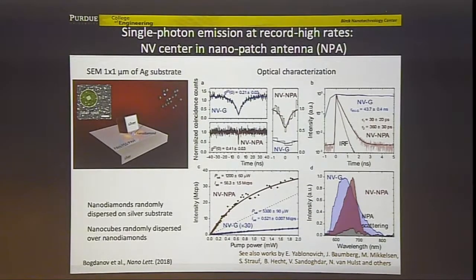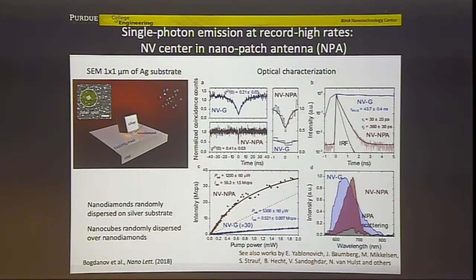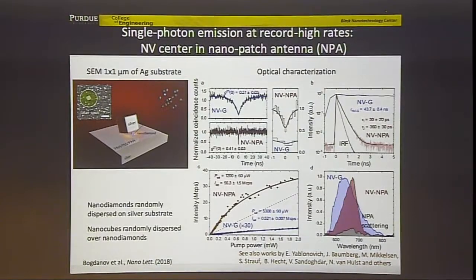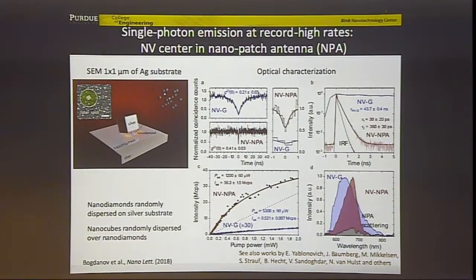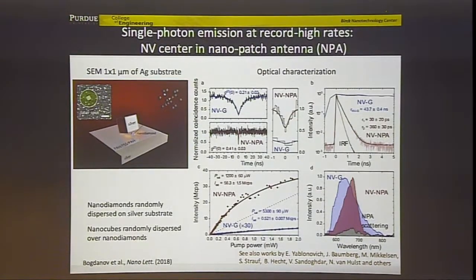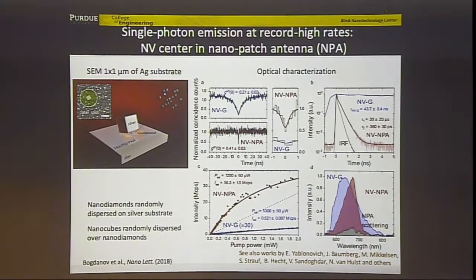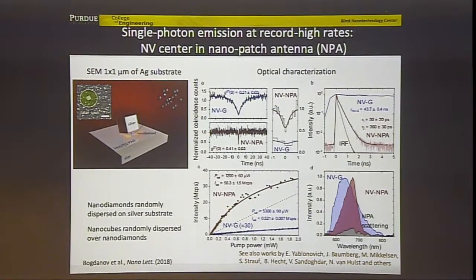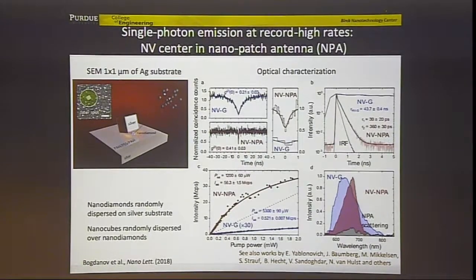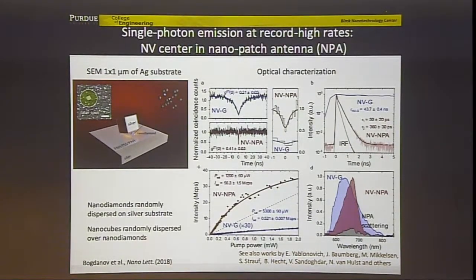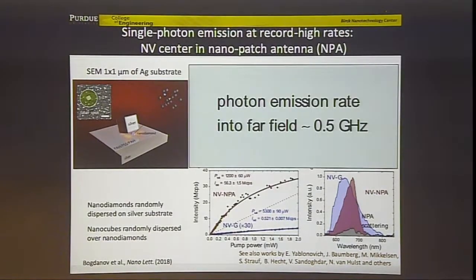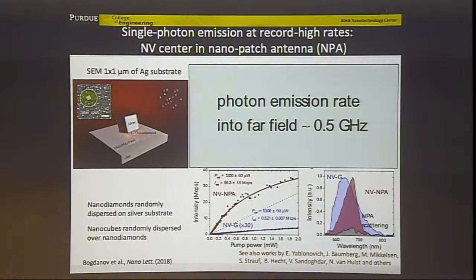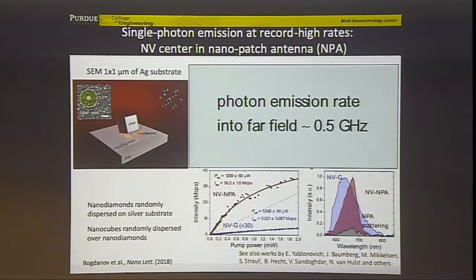And we see like 30 million counts per second, which is the highest rate of emission of single photons at room temperature observed so far. If I take into account that the efficiency of the photodetector is 70%, the collection angle is 50%, and the transmission of all optics used is 25%, the actual amount of photons emitted is 500 million single photons per second, which is a very huge number. But this is far from being optimized.